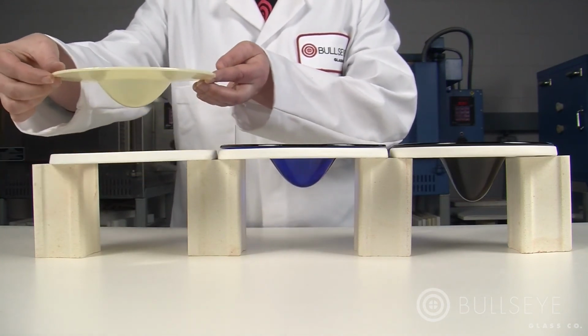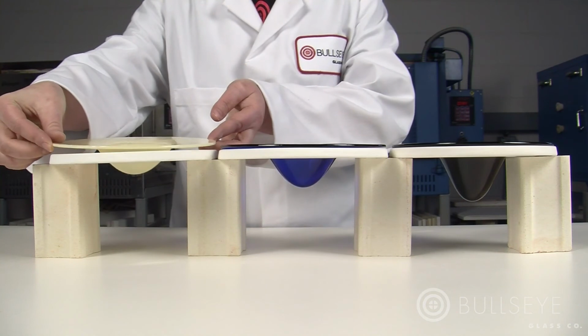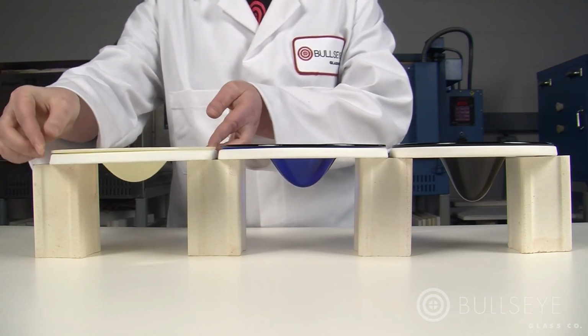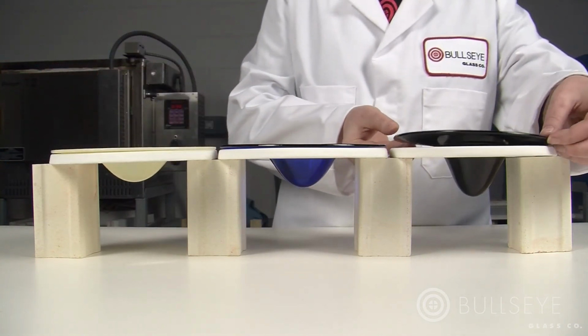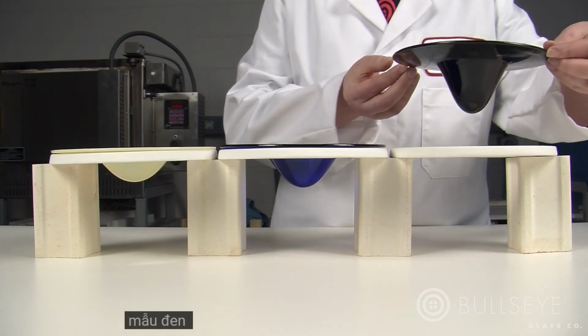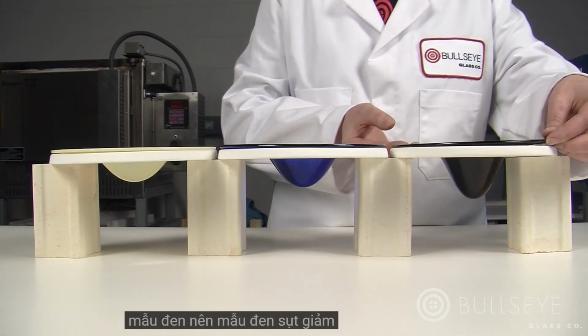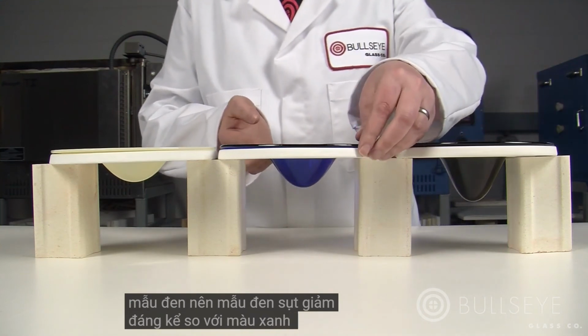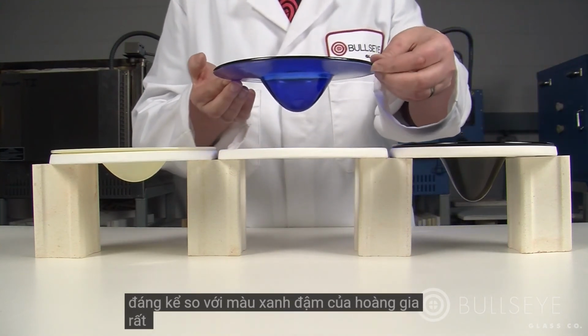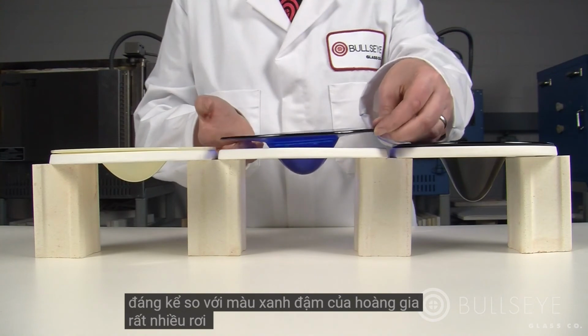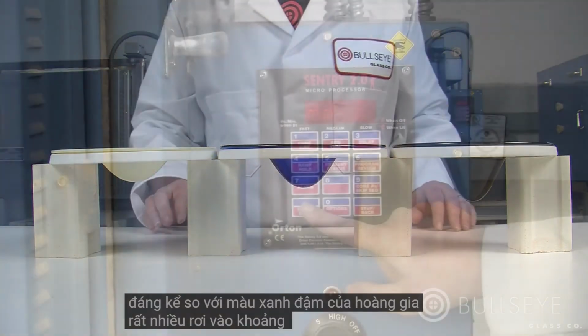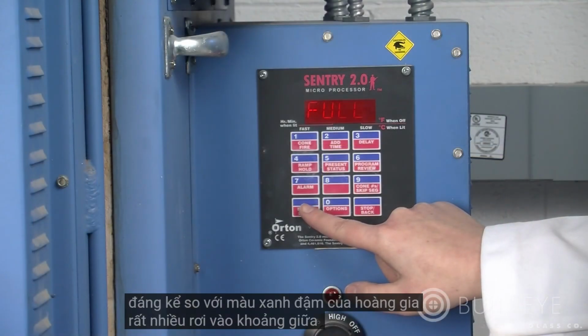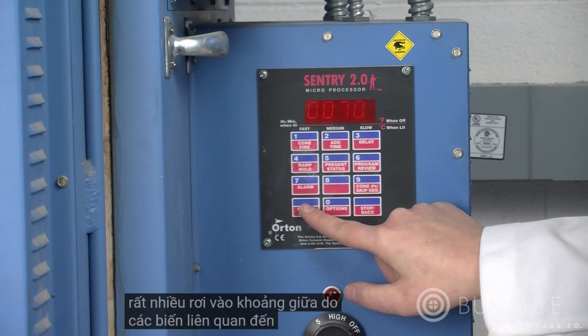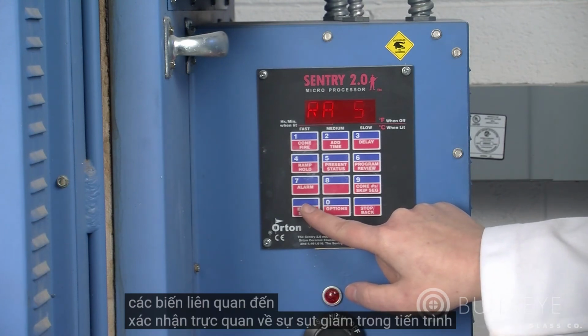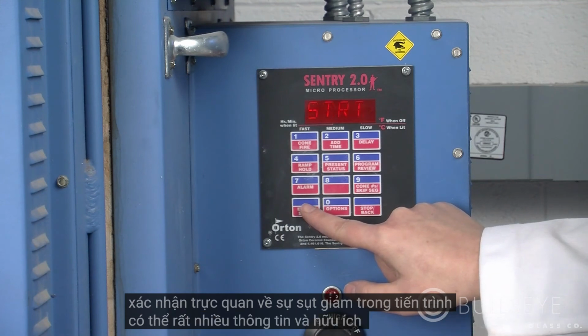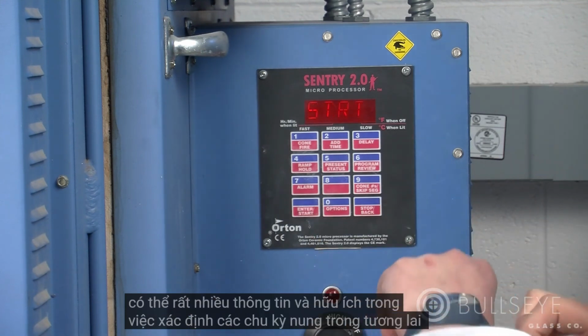These samples were slumped in dropout molds using the same firing schedule. The French vanilla sample has a higher viscosity in the slumping range than the black sample, so the black sample slumped significantly more. The deep royal blue sample falls somewhere in between. Due to the variables involved, visual confirmation of slumping in progress can be very informative and helpful in determining future firing cycles.